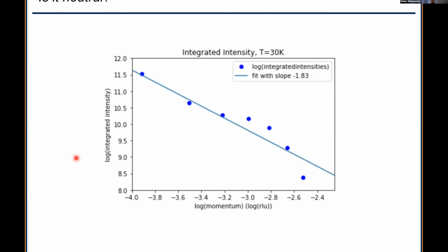So if you fit that with a line, you get a power law of -1.83. And -1.83 is greater than -2. So based on this, which I have shown in public for the first time, so I'm very interested to hear what I hear, it seems to be consistent with the mode being neutral.